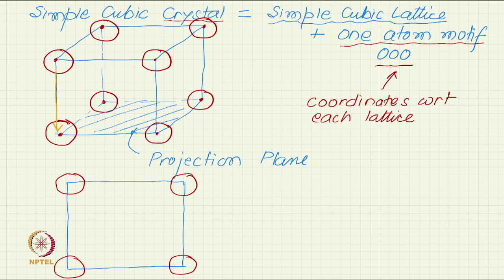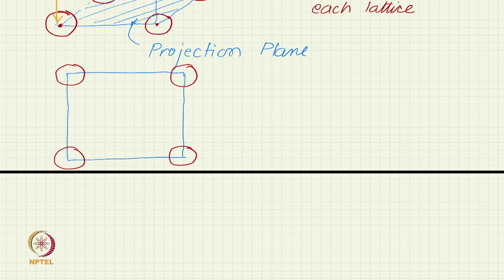And if I am not writing anything as coordinates of these points, x and y coordinates are visible. So, I have to label x and y. So, let us say this is x, this is y, and z is of course the projection direction, going out of the plane, normal to the plane. So, the x y coordinates I do not write usually, that is the convention in crystallographic projection, because the x coordinate is visible, that I have gone all the way to the end of the unit cell edge length. So, the x coordinate is 1 for this atom, for example. Since I am on the x axis, the y coordinate is 0. So, x and y coordinates should be readable from the projection, but are usually not written. What should be written is z coordinate, but again the convention is that 0 or 1 z coordinates are not written, only fractional coordinates are written.